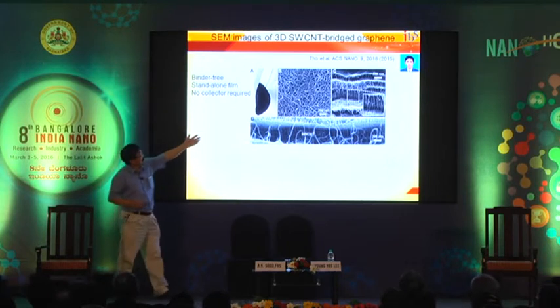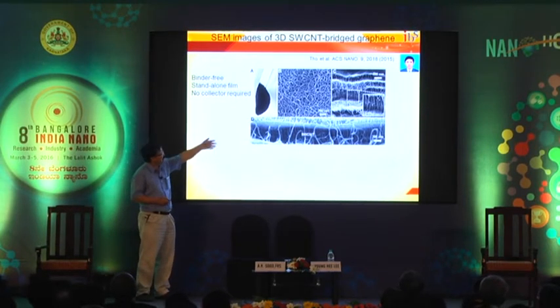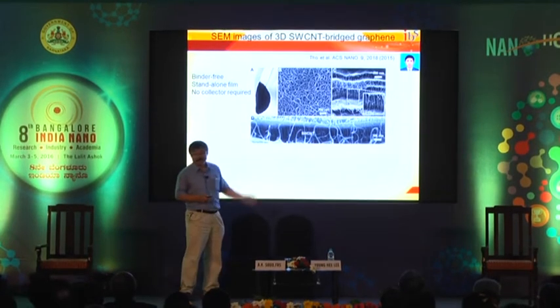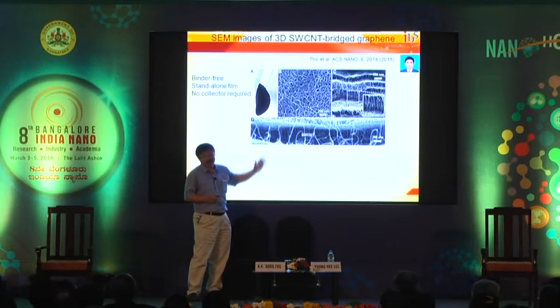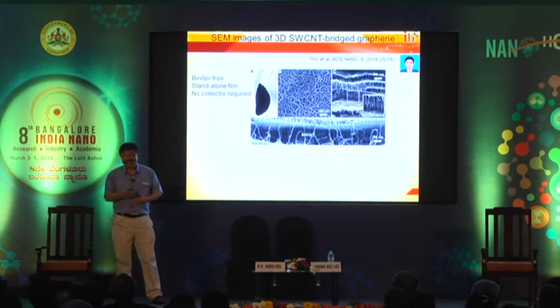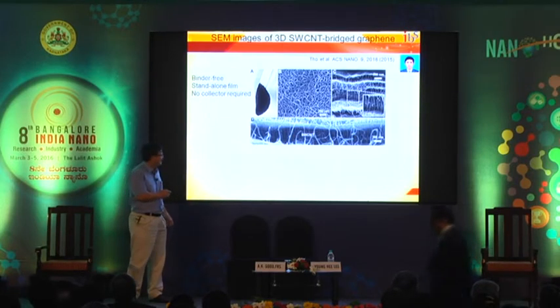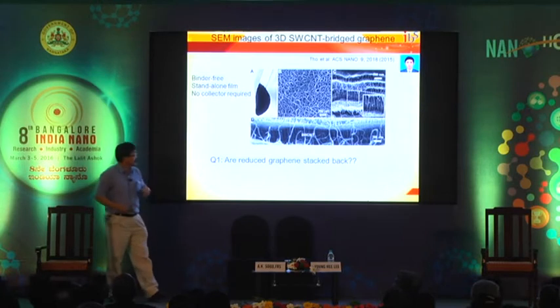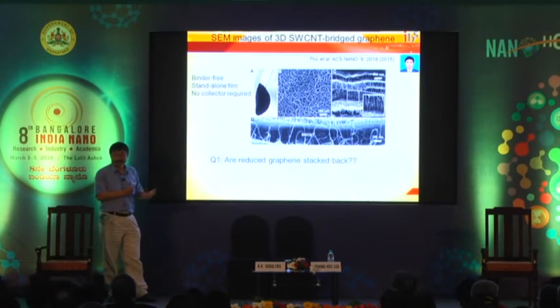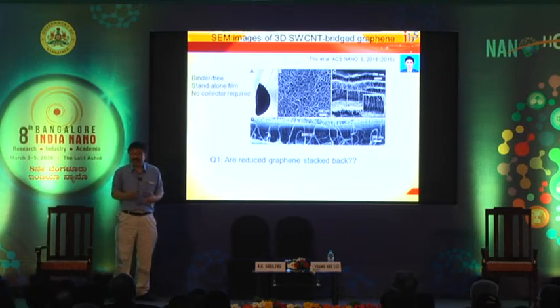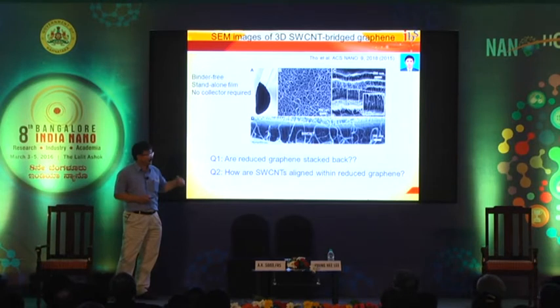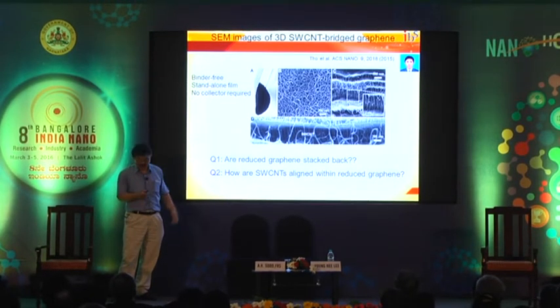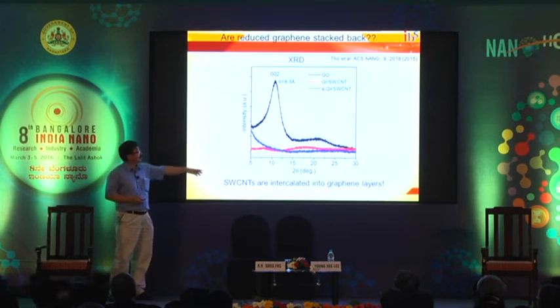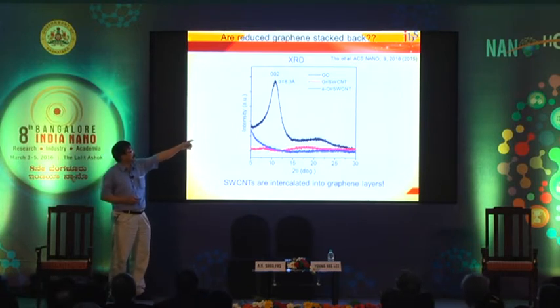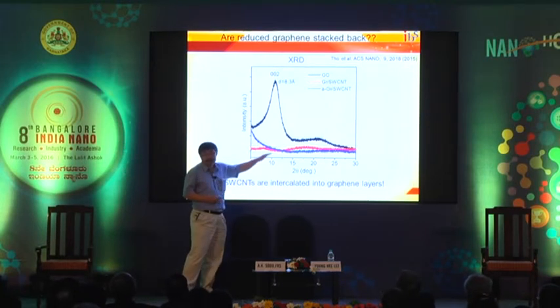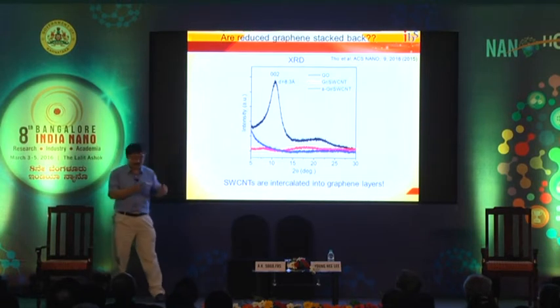By looking at the SEM on top, you cannot see much. It's just a random network of nanotubes. But if you look sideways, by cutting, you see nanotubes are aligned like this. Of course, this can be created during the cutting, so you have to argue whether this is really aligned or not. Anyway, we have two questions. One, when they got stacked together by this electrostatic interaction, did they simply stack back again? And another question is, are these nanotubes really aligned perpendicular to graphene? When you look at this XRD, with the activated graphene nanotubes, that is the blue line, you see there's no peak. That means they are not aggregated back, which is a good sign.